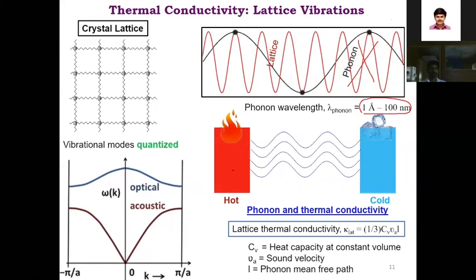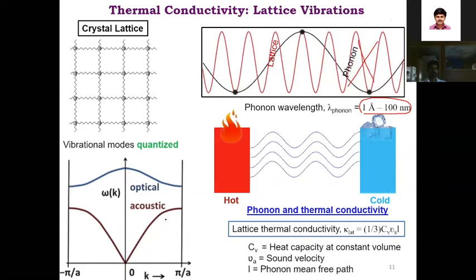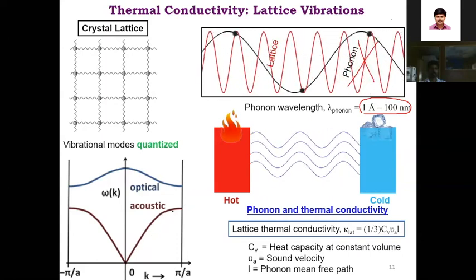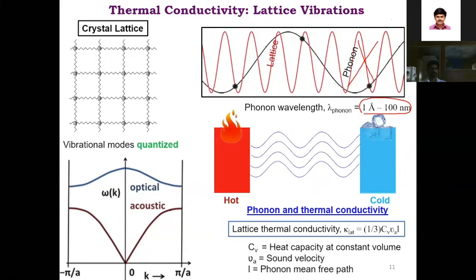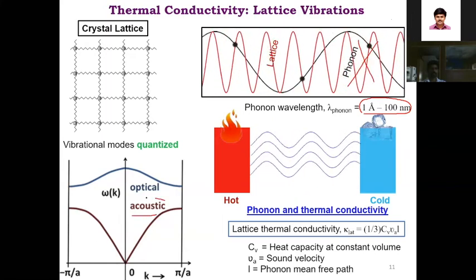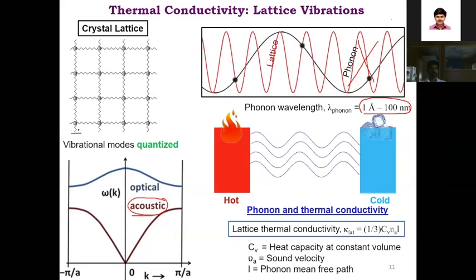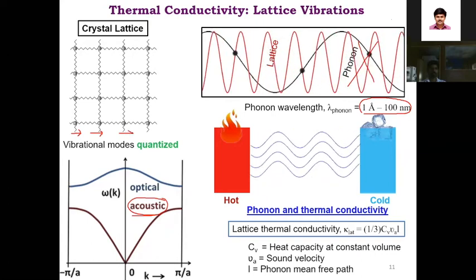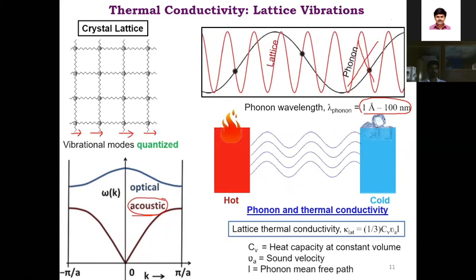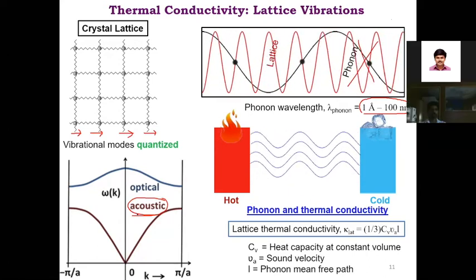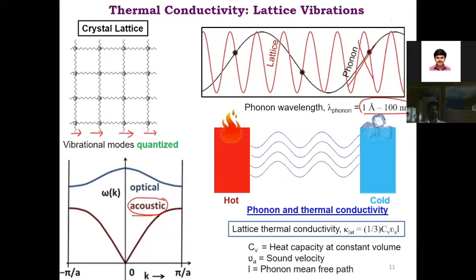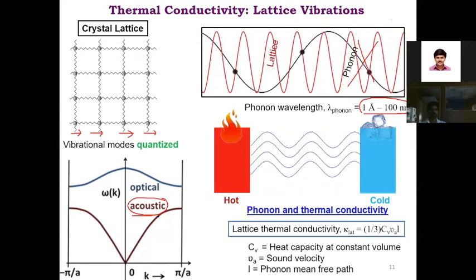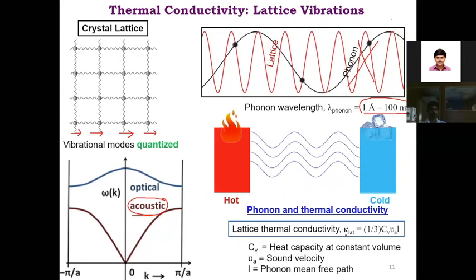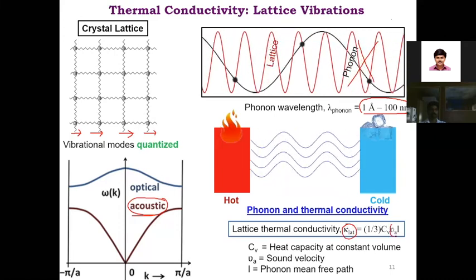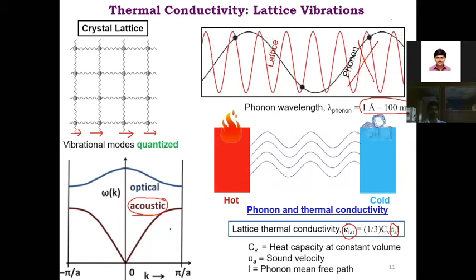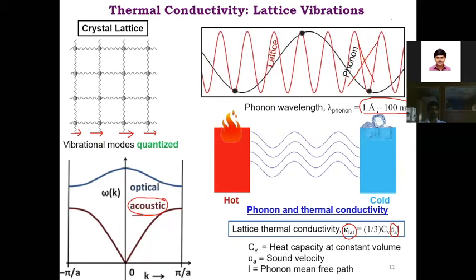Before going to that, another important thing we have to tell: there are two kinds of phonon. One is the acoustic phonon. This is a cartoon diagram which starts from 0. It's called acoustic phonon, as you can see from the name. Acoustic phonons are when all the atoms in a lattice vibrate in the same direction, and this is directly related to the sound velocity in a solid material. So you can calculate the lattice thermal conductivity if you know the sound velocity of a solid material, and acoustic phonons have this mean free path which actually carries the heat in a solid material.